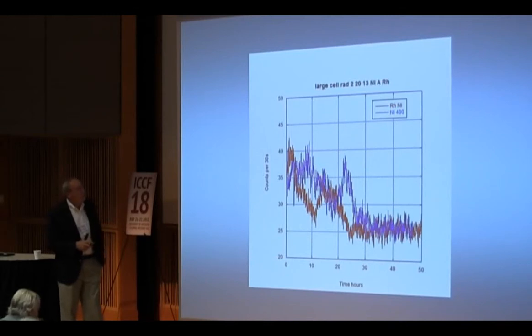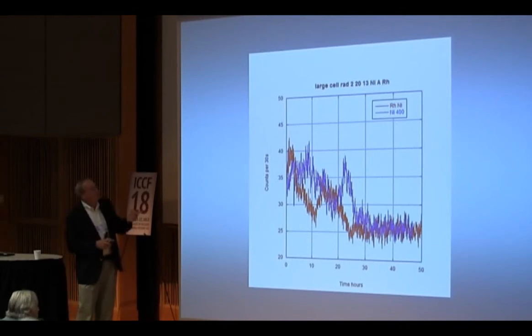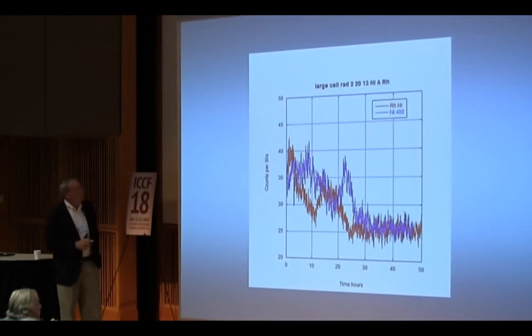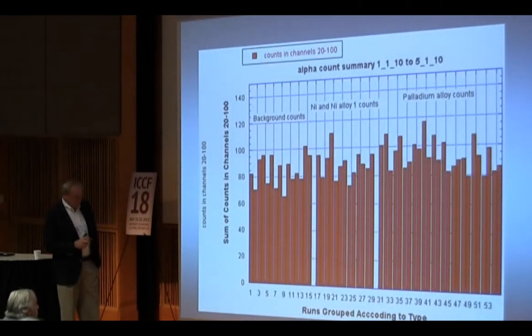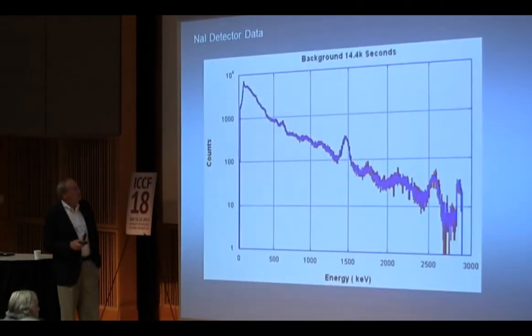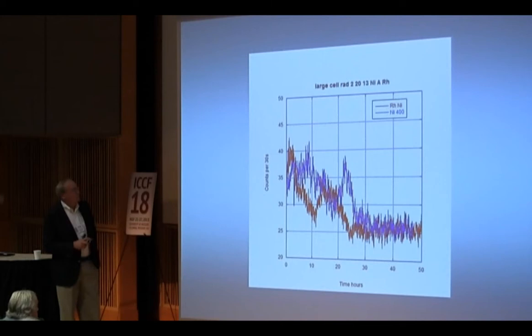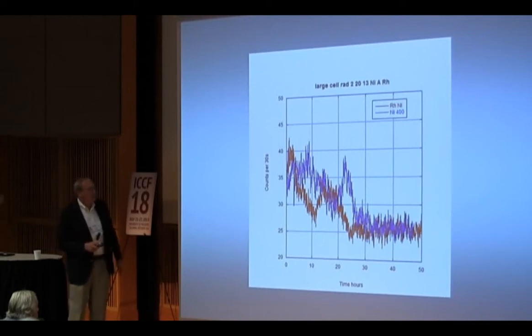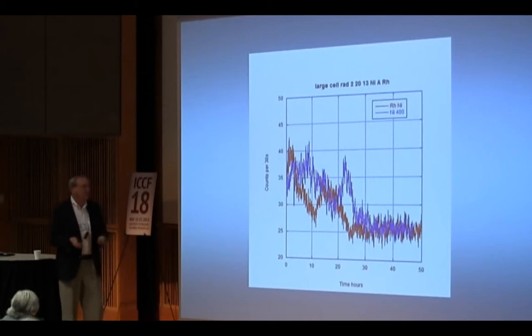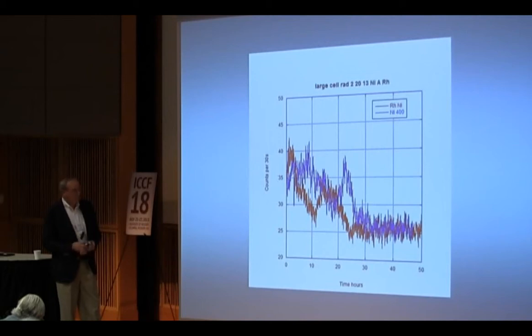This is what we get in nickel samples. We have activity that only lasts for maybe 24 hours or so. So after this, the activity is very low. And I've seen this a number of times. If you run these samples longer and longer, the output is lower and lower. But in the beginning, you've got some activity.